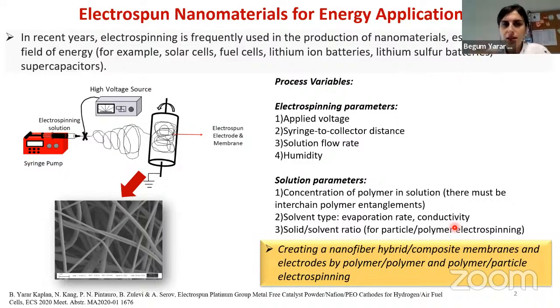What we can obtain from this electrospinning setup in the energy application is nanofiber hybrid composite membranes and electrodes by polymer or polymer particle electrospinning. Actually, we are conducting polymer electrospinning for the membrane part, and we are using polymer particle electrospinning for the electrode research.